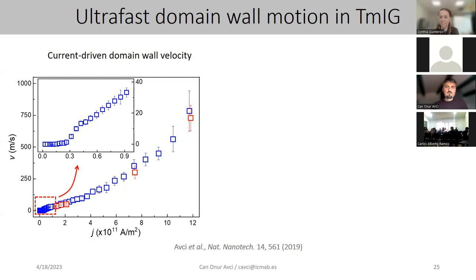GGG is a substrate which is commercially available. A pure GGG has a certain lattice parameter, I think 12.38 angstrom, but they also use some doping to tune that lattice parameter very precisely. So then you can match your GGG substrate to any rare earth iron garnet that you want to grow on top, if you want to obtain some strain. So that's for epitaxial matching with the substrate. And all of them have the very same topography, right?